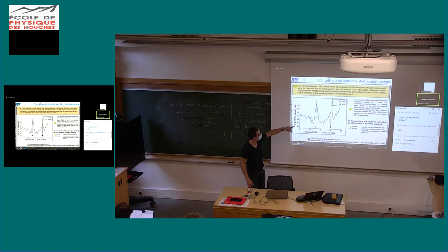For the aluminum side, in a full curve, and in the dotted curve is for the nitrogen side. They clearly identified two peaks at around 30 degrees and around 60 degrees that will tell that this polarity is the aluminum side. So we will try to reproduce that kind of curve.